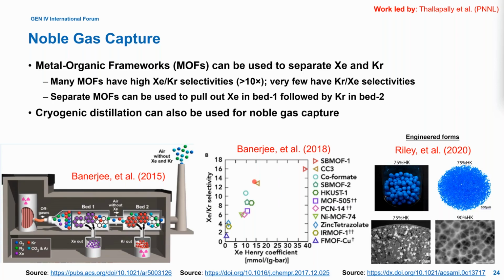And so putting those in some sort of a flowing stream is difficult because they'll transport downstream. So one option is to create some sort of a mechanically high integrity engineered form of these materials. So this is one option where we took polyacrylonitrile and it creates this very fine net porous structure. It's a polymer, and so you can embed your MOF crystals inside this polymer.